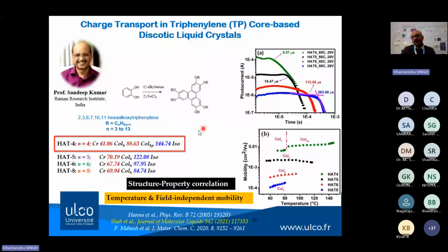So what happens if you change the alkyl chain length? If you increase or decrease the alkyl chain length, you can prepare different homologs of these compounds. Here we have varied the alkyl chain length from n equal to 4 to n equal to 8. When you increase the alkyl chain length from n equal to 4 to 8, the isotropic temperature got reduced. This is a typical behavior of structure property correlation. This particular compound is very interesting because the alkyl chain length is shortest, and it presents a very highly ordered phase. It showed a hexagonal plastic phase, which is the most ordered phase in the hexagonal family.